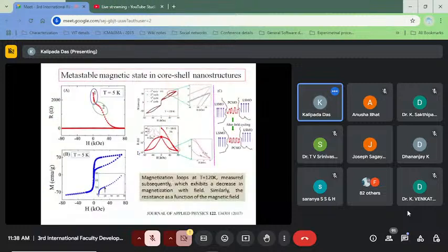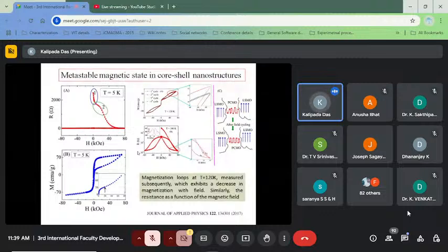And also, the metastable state in the core-shell nanostructure is given here. At 5 Kelvin, we measured resistance as a function of magnetic field in the core-shell type sample. We see that first, when starting the measurement, circled by 1, the resistivity goes down very rapidly. This is possibly due to the ferromagnetic LSMO part. The part marked as 2 is possibly due to the charge ordering melting of the PCMO host matrix, and then it goes to the metallic state and remains in this state.